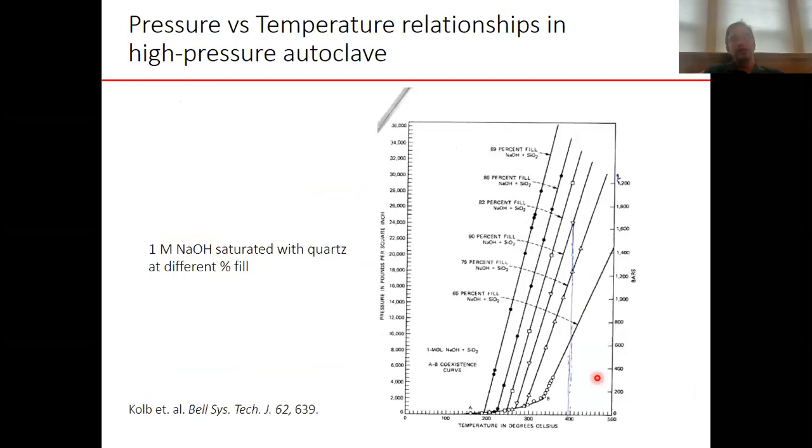All right. So let's look at the hydrothermal crystal growth in a little bit more depth. What I have forgotten to say is, of course, that in the autoclave you also have a mineralizer. That mineralizer is typically either a sodium carbonate solution or a sodium hydroxide solution.